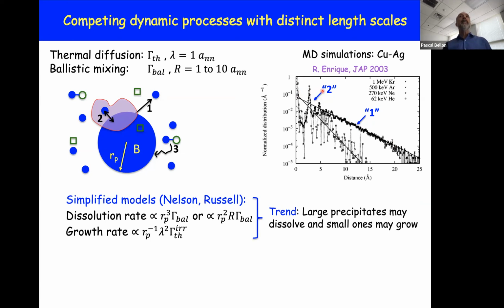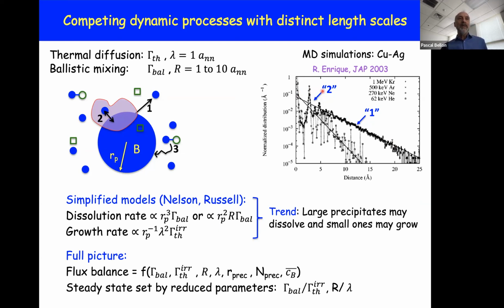What I want to impress upon you is that there are a lot of parameters that control the evolution of the systems, but there are 2 key reduced parameters that capture this competition between thermal diffusion and ballistic mixing. One is the relative rate of mixing over thermal diffusion. When the relative rate is high, we are promoting mixing at the expense of thermal relaxation or precipitate growth. But it's a competition through rates, and it is also essential to realize that there's a competition of these processes through their distinct length scales. The mixing has an intrinsic length scale R that can be several times larger than the intrinsic length scale of thermal diffusion, lambda.